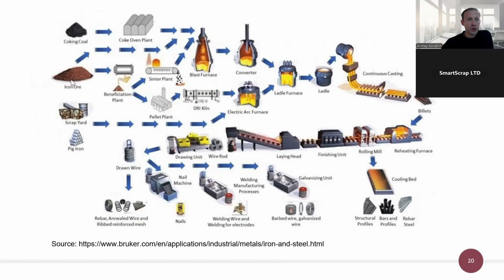Iron ore has low Fe content, iron content, and it goes to beneficiation plant to increase iron content in iron ore concentrate. Then this material goes to sinter plant for the production of agglomerates, and this raw material as agglomerate and coke goes to blast furnace. After blast furnace, we have liquid iron, and liquid iron goes to the converter, or in a different name, basic oxygen furnace, and it is mixed here with scrap in proportion 70% of liquid iron and 30% of scrap. And it is a secondary metallurgy. Let me come back a little bit later.